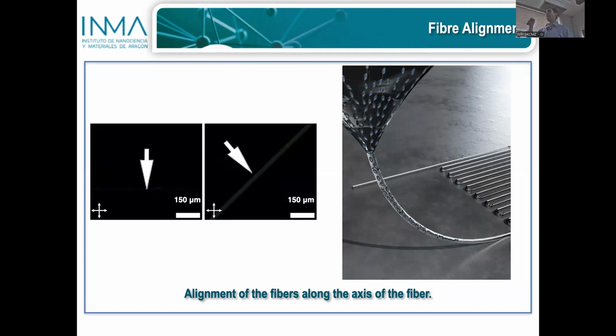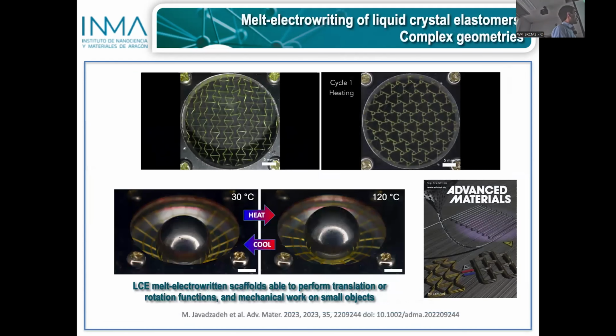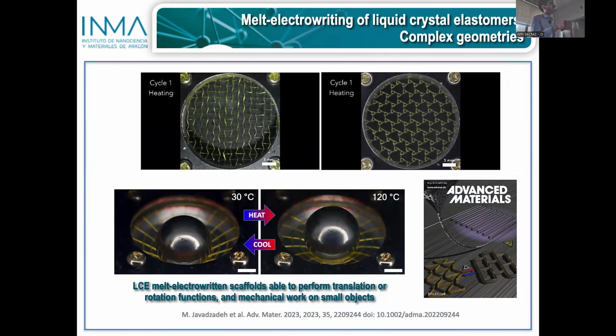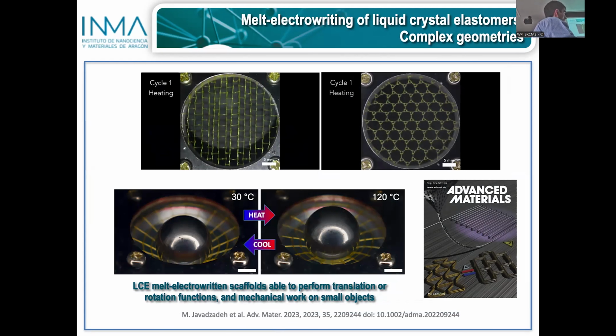So again, we gain a digital control of the morphology of the material in our structures that allows us to generate structures that respond mechanically on heating, as you can see in this couple of videos in which you have this auxetic structure that is framed, and therefore it generates this rectangle, or you have this anti-chiral structure that on heating makes the nodes rotate clockwise or counterclockwise depending on the node. Also, the system is able to generate a significant amount of work. As you can see, this small spider net is able on heating to raise this steel ball.